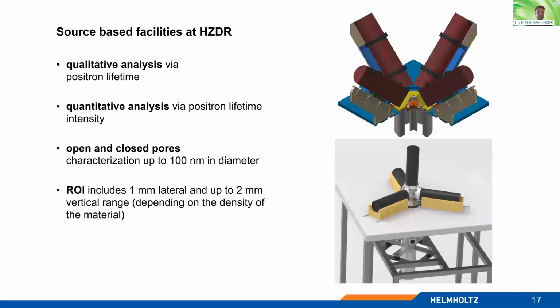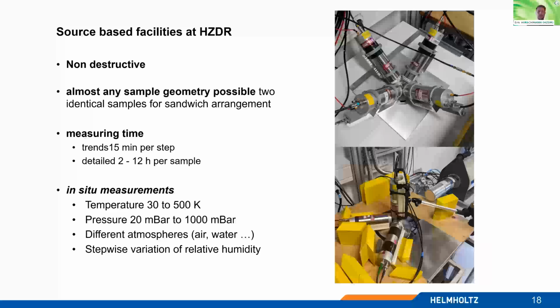Coming to details of our setups, we have 2 setups at the moment, working with 4 tubes, which increases the solid angle and decreases the time per measurement. As I said, we can measure open and closed pores up to 100 nanometers. And the region of interest, which can be investigated with this kind of setup, is approximately 1 millimeter lateral and up to 2 millimeters in vertical range. But this depends highly on the density of the material. So high density material stops the positron earlier, and low density material needs a thicker sample or stops the positron later.